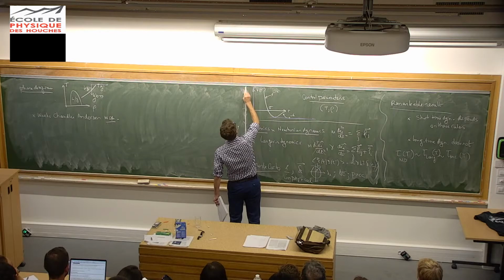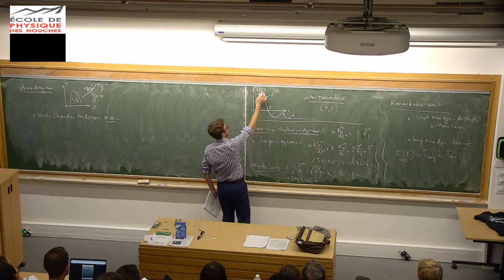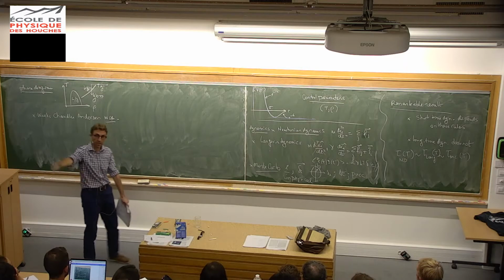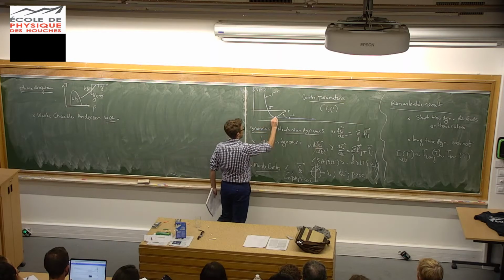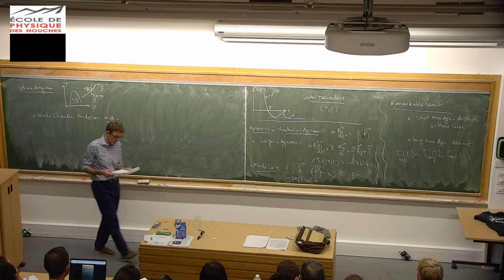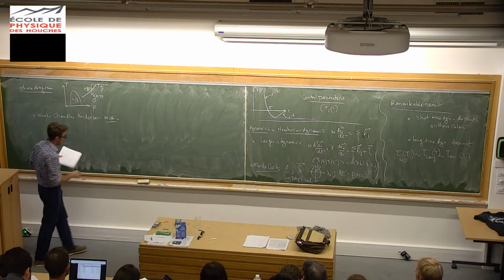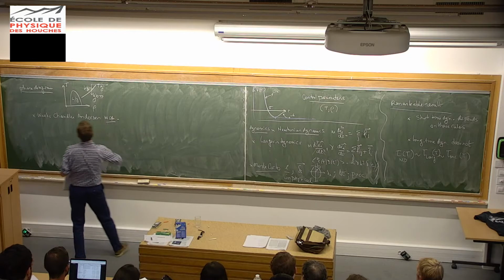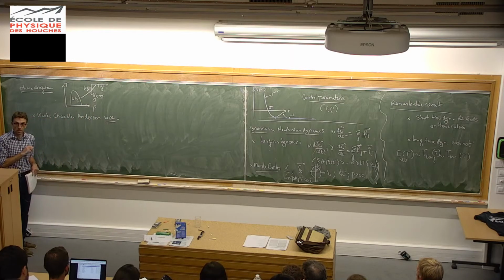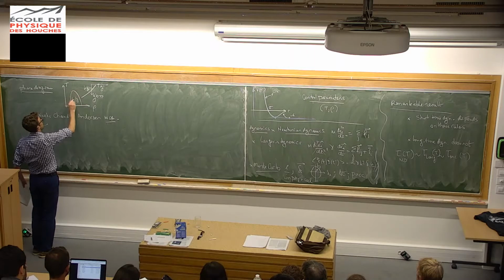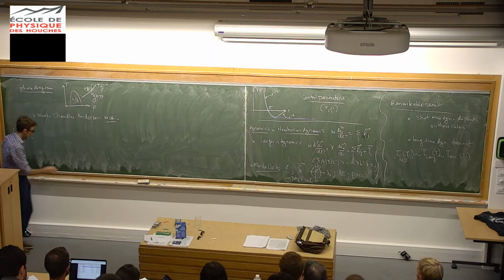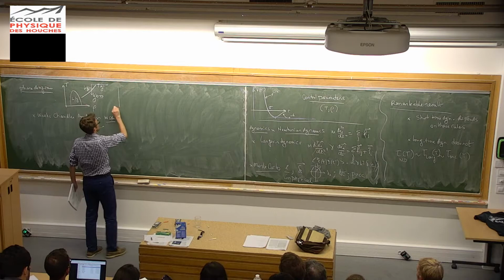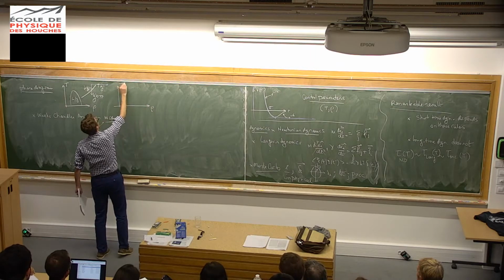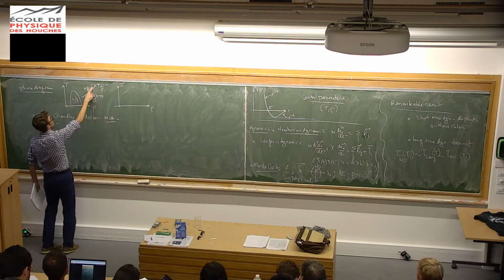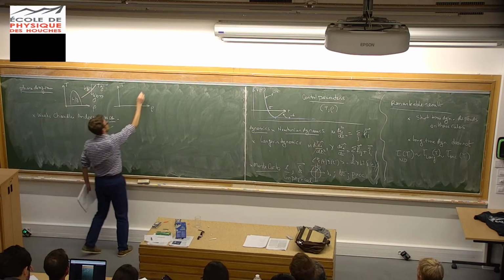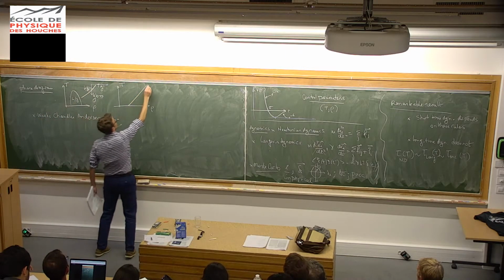So this is the WCA. At short distances, it has the same functional form as the Lennard-Jones, but at distances larger than this cutoff here, you remove the attractive part. So it's a nice model because you remove the attraction between the particles, you kill that part here. So the liquid-gas phase separation disappears. For the WCA potential, I really like this temperature-density phase diagram. You can follow this arbitrarily low in densities, and this is the result.